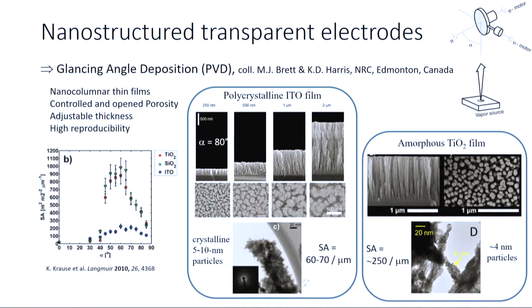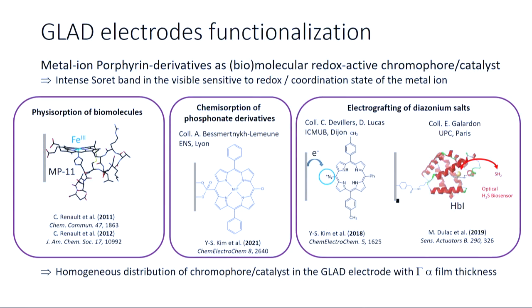So next, how do we get functionalized electrodes based on these metal oxides? Well, we worked mainly with metal ion porphyrin derivatives as biomolecular redox-active chromophore or catalyst. We selected these molecules because they have a very intense Soret band in the visible range, around 400 nanometer, that is sensitive to both the redox state of the metal ion as well as its coordination state.